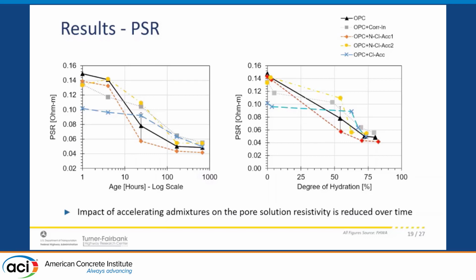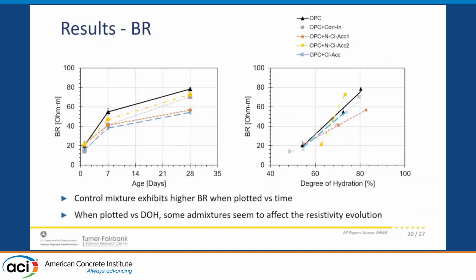These were promising results for us because we could show that we typically perform quality control around 28 days or even further, and by that time, the influence of the accelerator seemed to diminish a lot, so resistivity could potentially be applied to these mixtures.